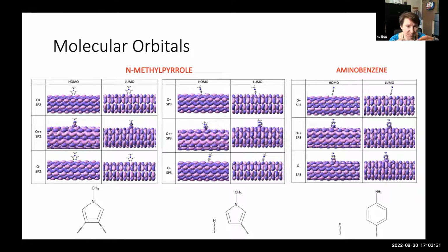So it has a triple bonded nitrogen attached to the place where the benzene now is attaching to the tube. And this nitrogen is gone, creating a radical, and then the radical attaches to the surface of the tube. So the reason why, for amino benzene, people believe it's attaching through sp3 and it is not possible to get sp2, it's just the way the reaction goes. People know this reaction. One can imagine many attachments, but not all of them were realized experimentally. Challenging.